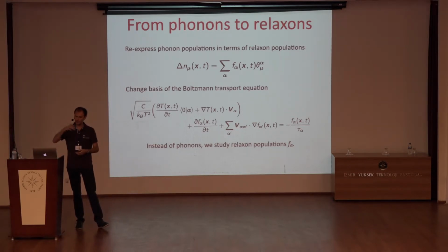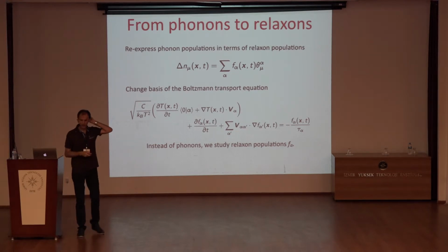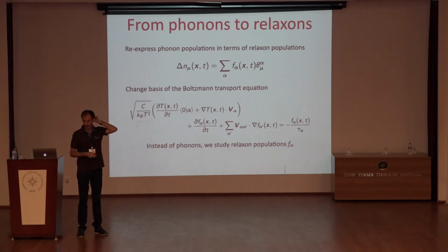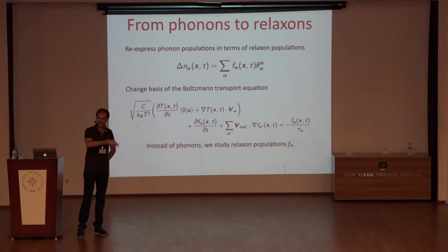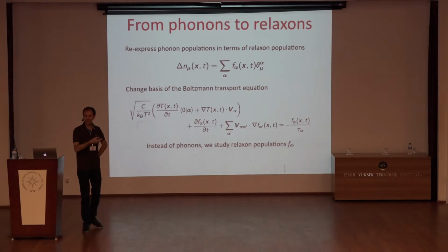It's not easy to just give the intuition, but you can expect at high temperature, when you go close to the classical limit, that there are some Bose-Einstein distribution functions appearing inside the expression for the scattering matrix, which if you expand at high temperature, then you see that the temperature dependence is something like 1/T.